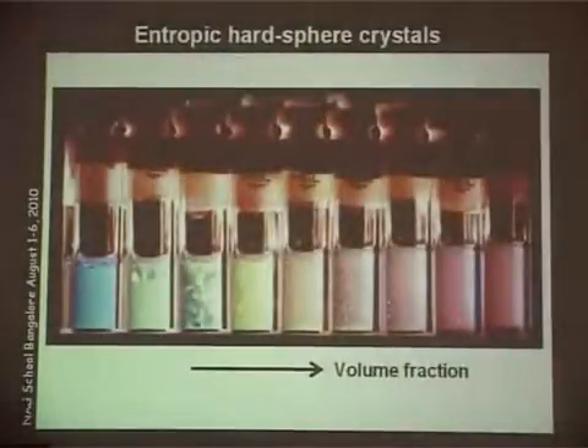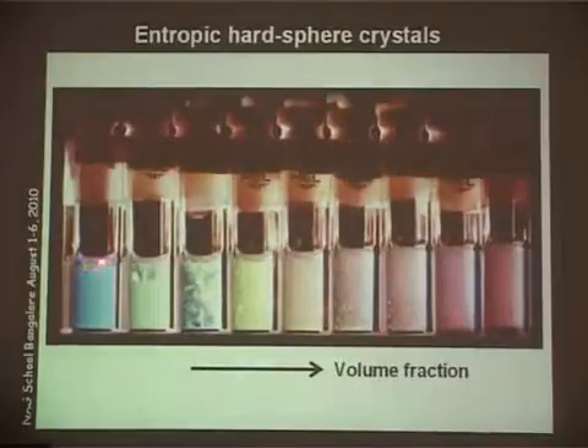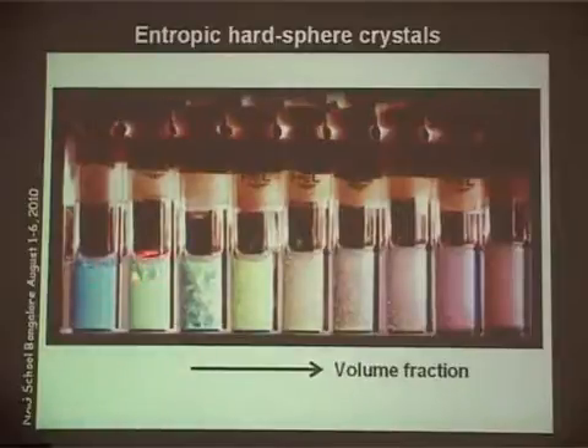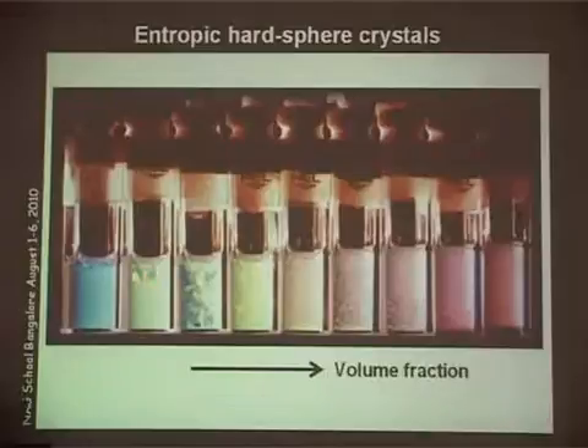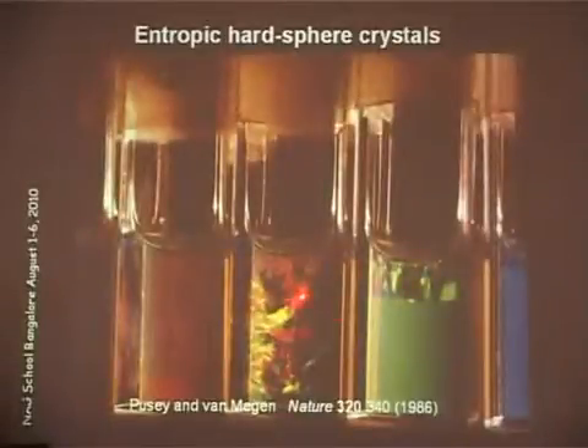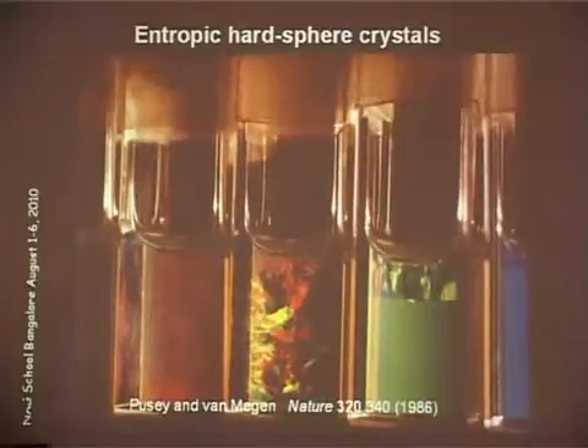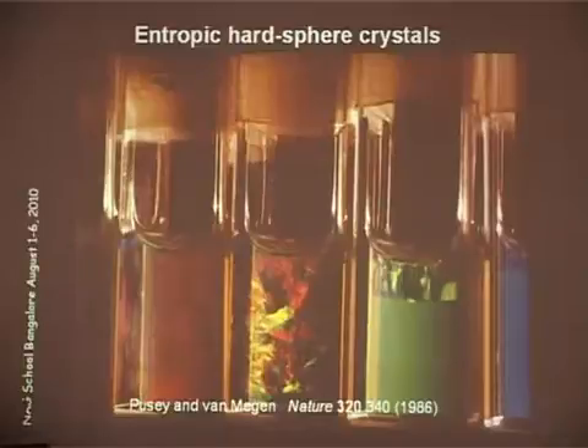Okay, so this was beautiful work by Pusey and van Megen, and they realized that in experiments, and you have seen that picture now many times. Again, here you have an onset of crystallization in coexistence with a liquid. The fraction of the crystals is growing, and here you see it very nicely because it's simply the Bragg diffraction from the crystals and so forth. And then you start to form a glassy region. Here the crystalline phase disappears. Okay. So just to blow up to show how beautiful it is. You see the crystals here. For some reason the crystals here are much smaller. But okay.